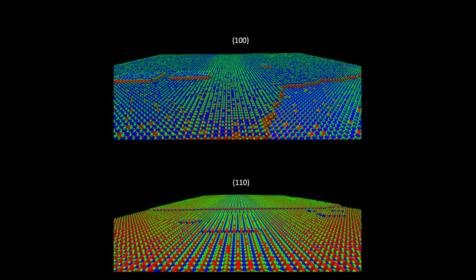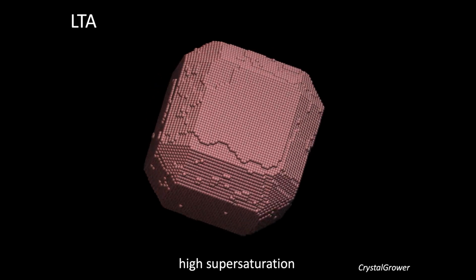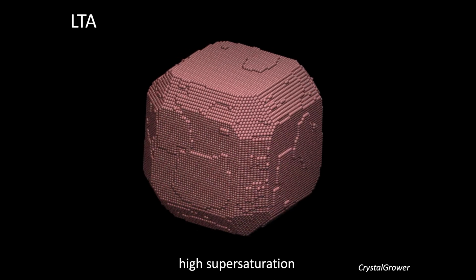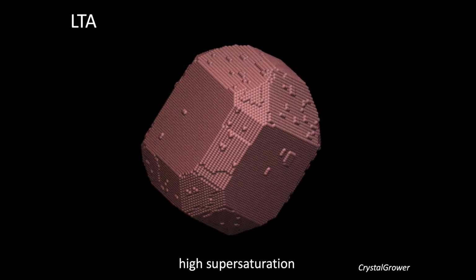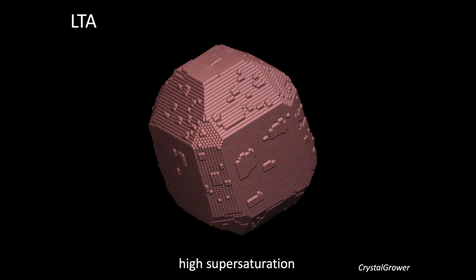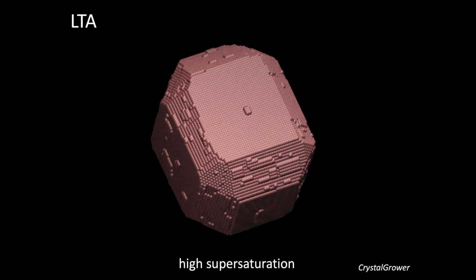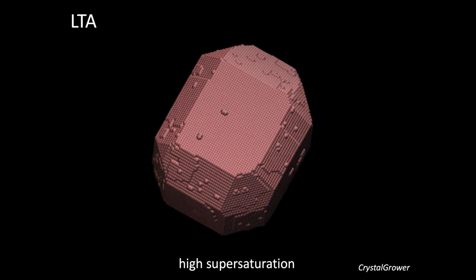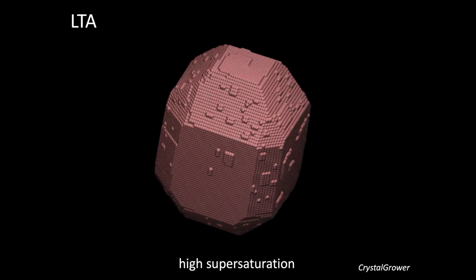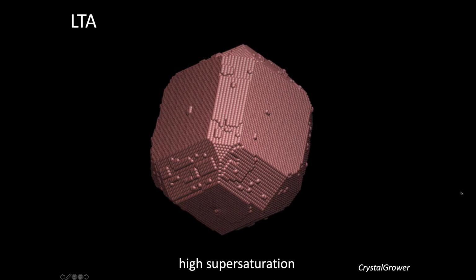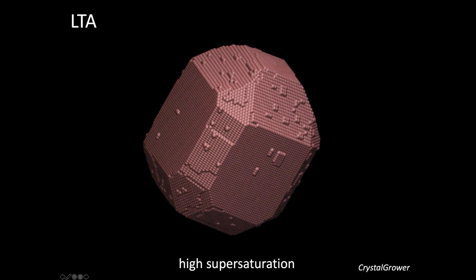We also get out from the simulation not only the topology but all the surface structure, and we can even look at the terminations, the crystal termination which comes out of the program. And we can do that under different conditions of high supersaturation, we can add in, in this particular case, a screw dislocation running from the top of the crystal to the bottom of the crystal, and you can see as soon as we have added the screw dislocation, the crystal has lengthened along the direction of the screw dislocation, and that's because it's growing faster along that particular direction.